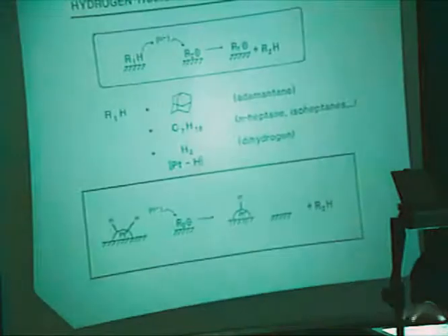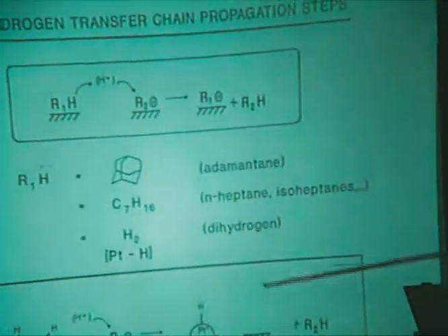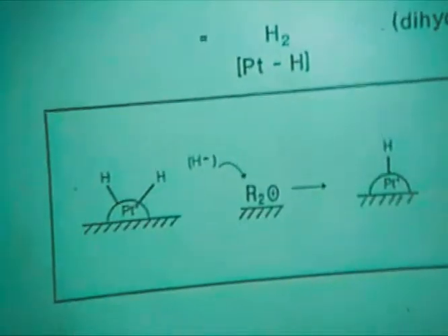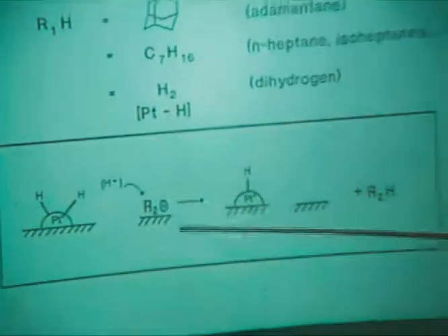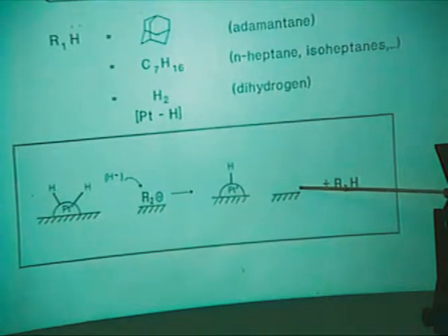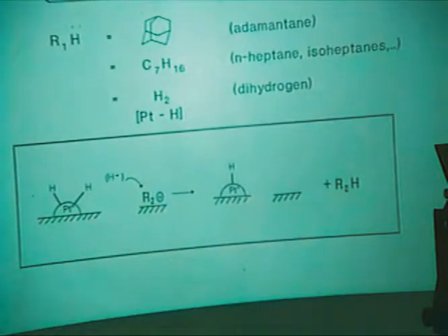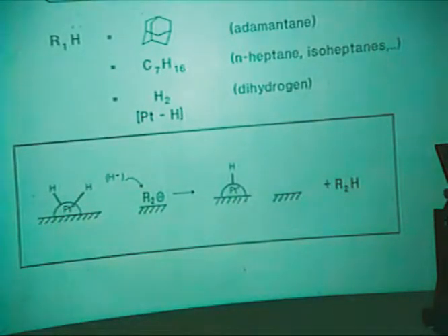In all cases, as I increase the concentration of any of those three, I get an increase in the rate of isomerization. It is acting as a co-catalyst. But look at the ranges that I have here for each one of them: 2,500 kPa of hydrogen, 250 kPa of normal heptane, 0.25 kPa of adamantane. This gives you an idea of the potency of those species as hydride transfer agents, but the fact is that all three of them are working in the same manner. They're working to terminate one of these carbocations and replace it with another one, and therefore lower the chances that it will stay there long enough to actually produce a cracking product. Well, this brings me for a second now to where Michelle's contribution came in, and hopefully I have the three or four minutes required in order to do it.